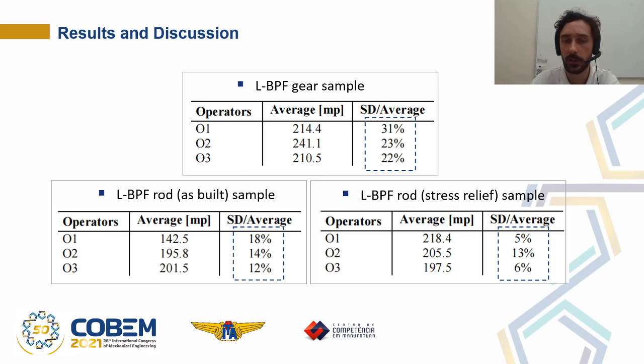And summarizing the results in three tables that relate the absolute mean of the signal to the standard deviation, it can be seen that the rod geometry contributes to the signal having less variability, and it can be estimated that the variability of the gear contributes to the signal deviation being almost double that of the rod samples.